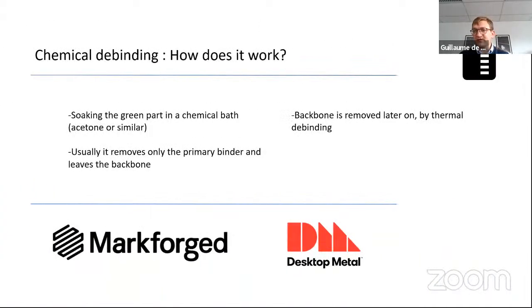So the other way, if you don't do thermal debinding, is to do chemical debinding. What happens when you do chemical debinding? So I'm sure you remember, I told you there is quite often two binders in the filament. Well, what you're going to do is soak the green part in a chemical bath, typically in acetone or other solvents, and this solvent is going to remove one of the two binders. It removes what we call the primary binder and leaves the backbone, and the backbone is later on thermally debinded. So when you put it in the furnace, you're going to burn it off. This is typically what Markforged and Desktop Metal are doing.